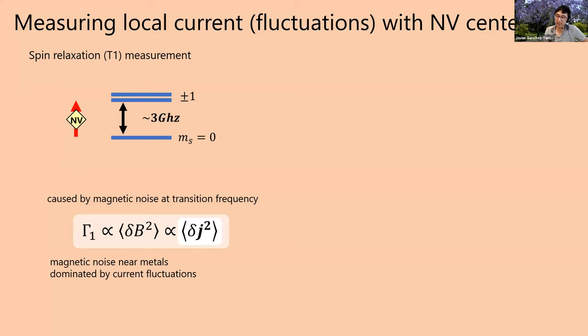So it doesn't involve a complicated pulse sequence anymore. This is what's known as a spin relaxation or T1 measurement. And the idea is that the NV center spin structure looks like the following. It has this m_s equals zero state, which is separated by 3 gigahertz from the plus/minus one states. And so what you do is something very simple.